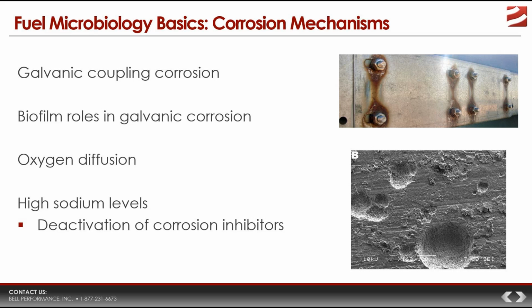Another thing, if you have high sodium levels in the tank water bottoms, and this is interesting, if the sodium levels in the tank bottom exceed, let's say, 0.1%, which is about 1,000 parts per million, this is linked to corrosion and to what they call soap formation. The acidic components, which are produced by the microbes, remember, will combine with the sodium and form these chemical soaps. What these soaps do is attack the corrosion inhibitors that have been added to the fuel, and they inactivate them, they break them down, which then makes it easier for corrosion to happen.